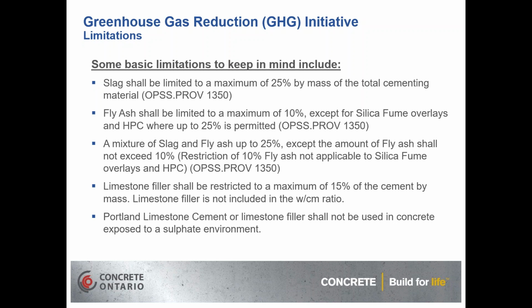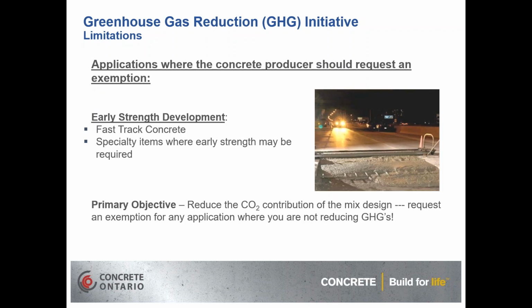overlays in HPC. The limestone filler is restricted to a maximum of 15% of the original cement content by mass. The limestone filler is not included in the water to cementitious materials ratio calculation, and the Portland limestone cement or the limestone fillers shall not be used together or separately in concrete exposed to a sulfate environment for the MTO works.